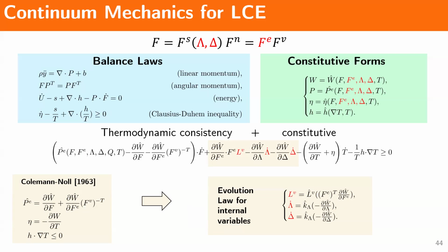What we can do here is see this as a product of our energetic terms as well as our rate terms. This is like your friction law. Basically, we can identify these two as conjugate pairings, where the energetic term is your thermodynamic driving force for your internal variables here. And so this lets us postulate an evolution law for the internal variables that we picked, these three internal variables, where the rate of each internal variable is dependent on the conjugate thermodynamic driving forces from our dissipation inequality.